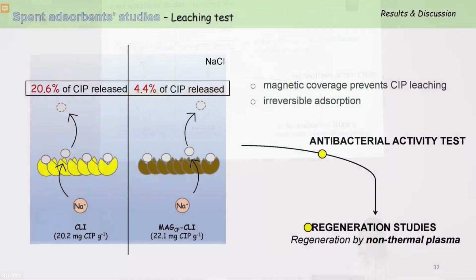The leaching experiments for 24 hours in sodium chloride solution show that only 20% of ciprofloxacin was released from the pure clinoptilolite, and only 4% from the magnetic clinoptilolite. This indicates that the magnetic coverage prevents ciprofloxacin leaching, and that the adsorption is mostly an irreversible process.